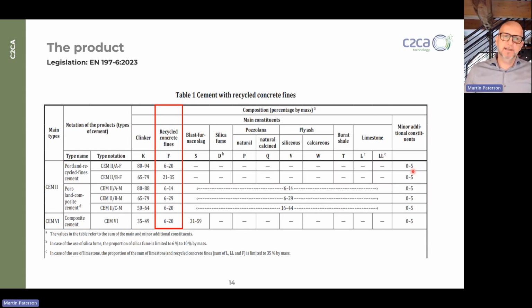Also, the legislation is partially in place, at least in Europe, and meanwhile in parts of the US. If you want to replace cement within a binder with recycled concrete fines, the EN 197-6 has been established last year, and it allows up to 35% replacement of cement with recycled concrete fines.